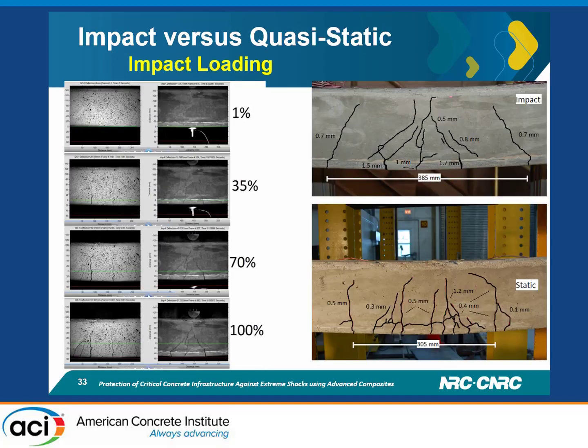And this is a comparison with the quasi-static. In the quasi-static, we use the same setup and exactly the same circular or cylindrical surface that we apply the impact load with. We simulate it in the quasi-static, but now we apply the load very slowly, and we compare based on the level of deformation in each case and how the damage develops. You can see in the impact a shear plug is formed in the top picture, and in the lower one it is regular flexure under point load.